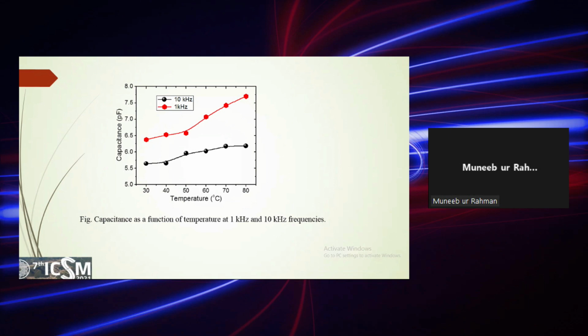that is why when we increase the external applied frequency from 1 kilohertz to 10 kilohertz, we see a drop in the capacitance of the device. So the reason is that at higher frequencies, only the electronic contribution remains, and all other contributions toward the polarization cease out due to the ionic, molecular, or orientational polarization. So that is why at higher frequency the capacitance of the device or the sensor is reduced.